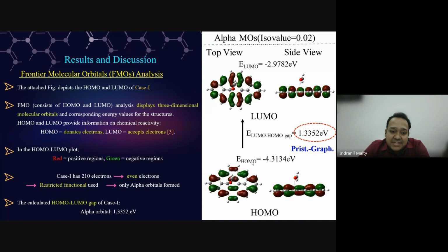In the case of pristine graphene, as the total number of electrons in the system is 210, which is even, the restricted functional was used, and here we have got the alpha orbital. The LUMO minus HOMO gap, or E HOMO-LUMO gap, was found to be 1.33 electron volt in the case of pristine graphene, as shown on the right side of the figure.